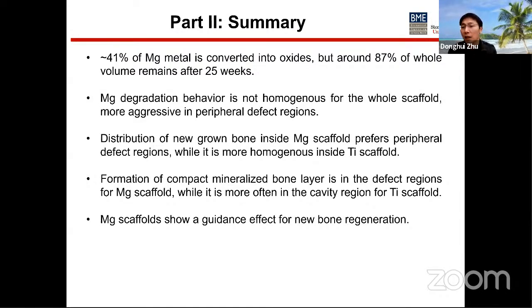The distribution of new grown bone inside the magnesium scaffold prefers the peripheral region, while for titanium it's more homogeneous. There's formation of compact mineralized bone layer in the defect region for magnesium, while it's more often at the cavity region for the titanium scaffold. The magnesium scaffold shows better guidance for new bone regeneration than the titanium alloy.